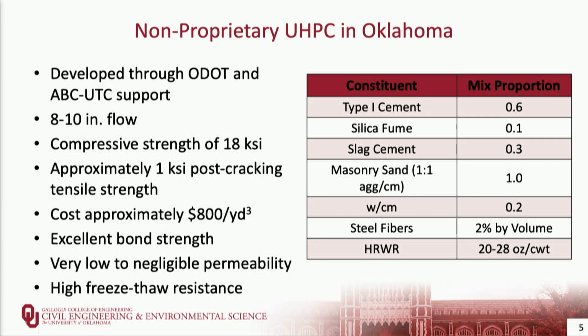sand, we were able to develop a UHPC mix design that could obtain a compressive strength in excess of 18,000 psi, a tension strength greater than 1,000 psi, and a cost of around $800 per cubic yard, compared to $3,000 or more for some of the commercially available products. It has excellent bond strength, very low to negligible permeability, and a high freeze-thaw resistance. I'll show you some of those results in this presentation.